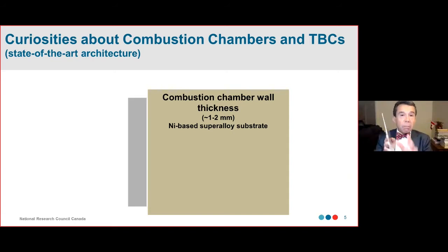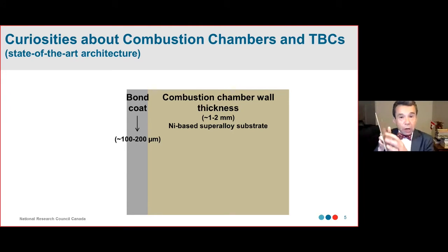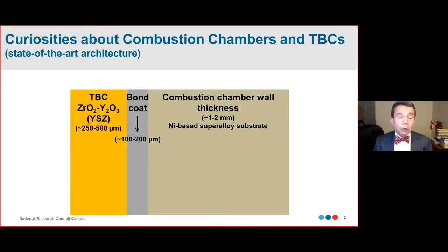And here, over the combustion chamber wall, you have a bond coat. It's basically a nickel-based alloy. The thickness varies from about 100 to 200 microns. And this coating protects the combustion chamber wall against high temperature oxidation. And here, over the bond coat, we have our ceramic TBC.